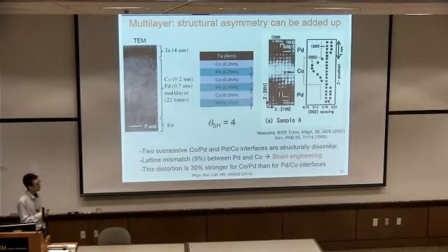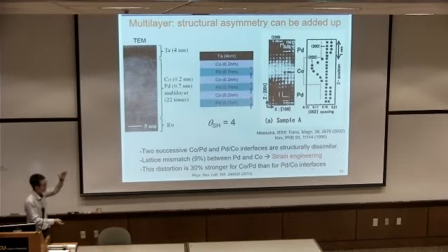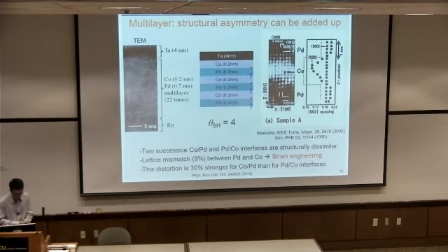Obviously this is very surprising, because theorists typically expect the palladium-cobalt and cobalt-palladium interfaces to cancel out, and then you end up with just the first interface. But that is a very naive theoretical picture. In real materials, you always have lattice distortion at these interfaces. And if you grow the multi-layer 22 times, as in our case, this strain distortion accumulates in the whole structure. So there is a huge broken symmetry in this multi-layer concept, and we attribute this large effect to broken symmetry from strain engineering.